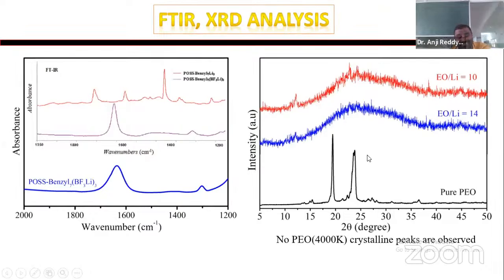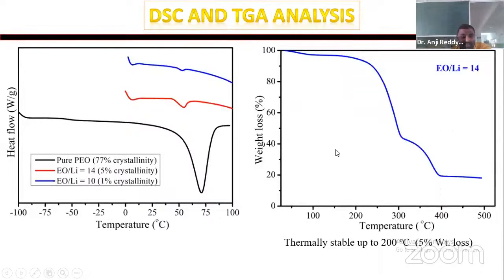That means the crystallinity is reduced maximally here. In the DSC studies also, the crystalline nature is high for PEO. After adding the POSS lithium salt, it reduces for different EO to Li ratios. The red one is ratio 14 and the blue one is ratio 10. You can also observe thermal stability: up to 200 degrees centigrade, the weight loss is only 5%. So this is thermally stable too.